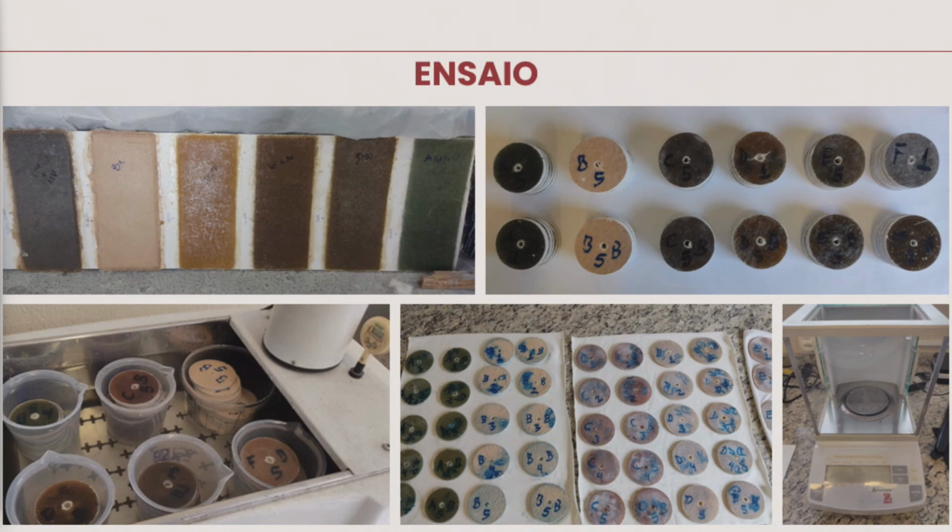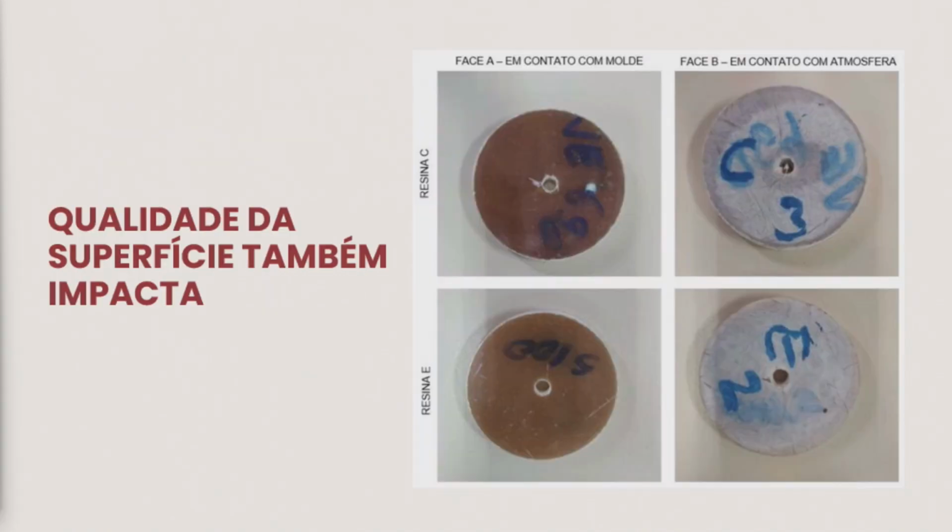We then used a circular saw and soaked them in a bain-marie at 60 degrees for 100 hours, and we precisely measured them. We allowed them to dry for 1 day, and then we weighed them once again. The weight difference is how much this test piece has absorbed in terms of water. So 0.00 whatever difference is however much was absorbed. And I did this with a range of resins and was able to make a comparison.